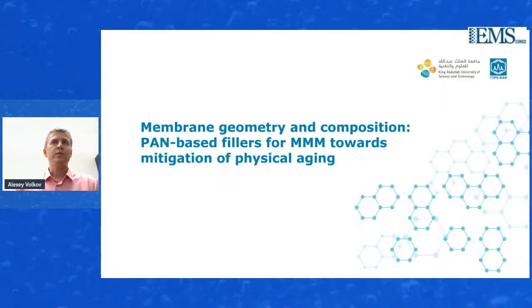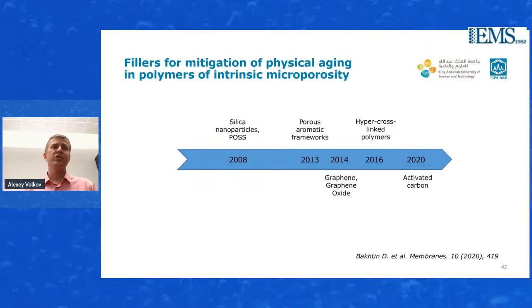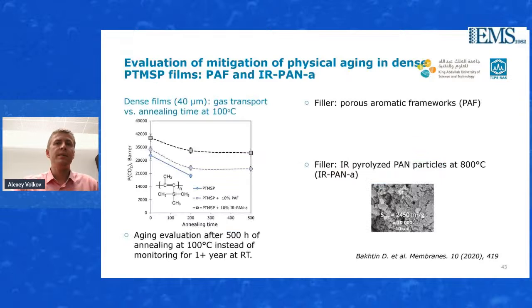And last but not least, that's an example of how we can use the PAN not only as a membrane material, but also as a filler. A filler can be used for the mitigation of the physical aging of the polymers of intrinsic microporosity, because as I said before, infrared treatment can also be applied for getting active carbon, and that's quite a filler with a high surface area, 2.4 thousand square meters per gram.